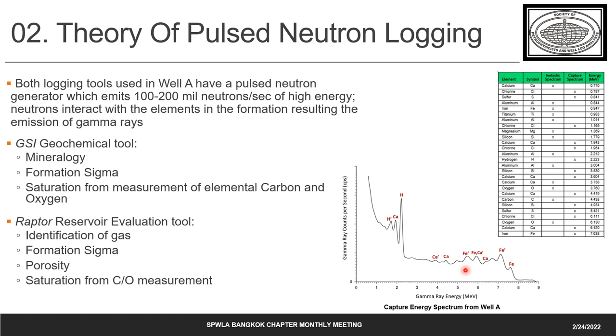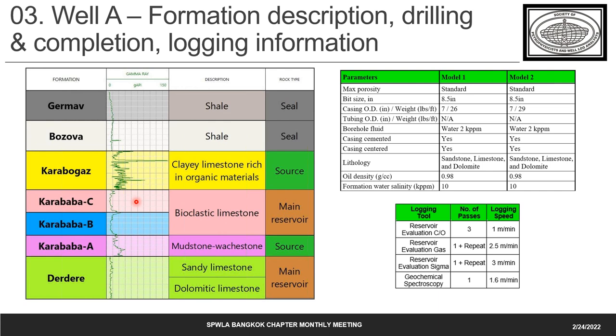and the inelastic spectrum from those spectrum. Using the matrix inversion, we determine the elemental standard. An elemental standard is a response of the tool to a single element. Then from the element yields, using the oxide closure method, we get the concentration that are used further in the analysis in order to determine the mineralogy. So here is just an example of how the elemental standards look like for different elements that was extracted from the total spectrum.